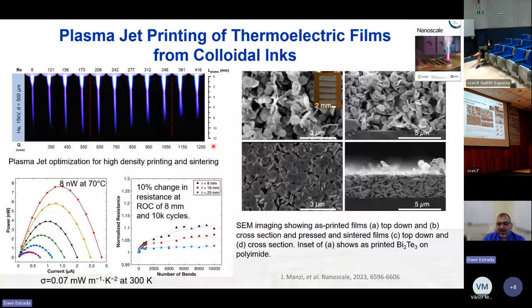Those details are in this Nanoscale paper here led by Jacob Manzi. But we show that at different gas flows, we can get different laminar flow regions for the plasma plume. And that does impact the quality of the print as detailed here. But probably the most interesting thing was when we did morphology analysis of the printed films through scanning electron microscopy, what we saw from top view and side view here is that the porosity of the film as deposited was about 90%. And so that plasma is charging the particles and creating extra porosity.